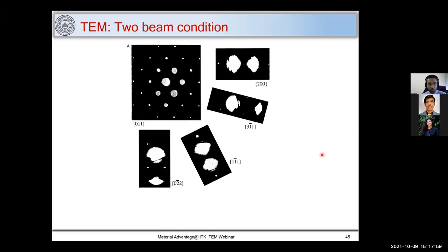Now let's consider a two-beam condition, which is very important to image dislocations. So the first thing, you get this symmetric pattern. And now if we want to get two-beam, let me explain it to you here. So let's say I consider these 1 and 2 points, which are marked here, and there will be Kikuchi lines also, which you can get when you converge a beam. Let's say this will be a Kikuchi line here. So when I want to get only these two spots bright, what I do is I move along this Kikuchi line. There will be a Kikuchi line here, and I move here. So I will end up getting these two diffraction spots brighter.